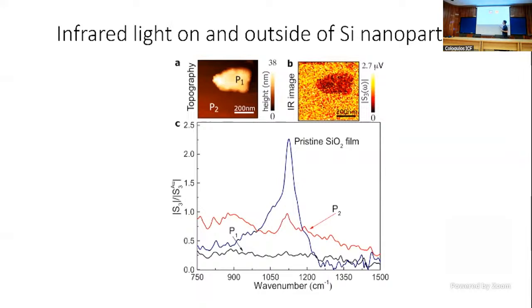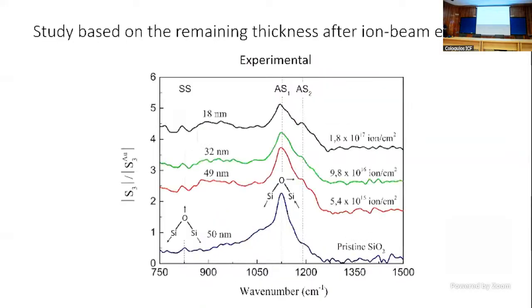Here, it's basically flat, and this flat behavior is what we expect for silicon. And the amount here is also consistent with silicon. So we are seeing that disproportionation reaction. We have these two things that have shown up here. Finally, we got a reason to use this technique.